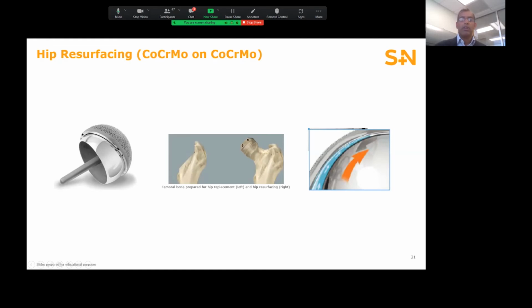Similar to ceramic on ceramic devices, the design philosophy here is to incorporate small diametric mismatch between both components to promote fluid entrainment. The sizes offered are large anatomic sizes. So this is beneficial from a stability standpoint, so it reduces dislocation risk. And it's also beneficial because you'll have greater surface velocity, which will also be beneficial from a lubrication standpoint.